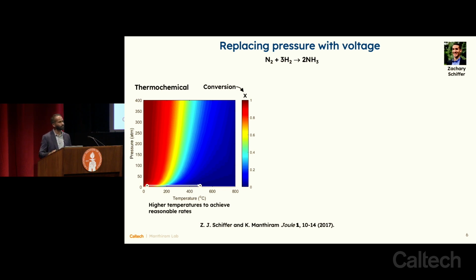But you can see the problem based on this plot, which tells us just the thermodynamic reality here, which is that we have a very, very small equilibrium conversion. That sure, the bonds are breaking and forming, and that's all happening from a kinetic perspective, but we stop at a less than 1% single pass conversion if we are at 500 degrees centigrade.